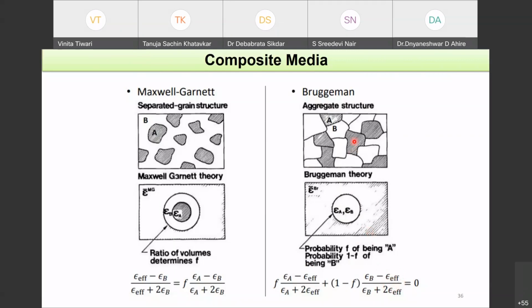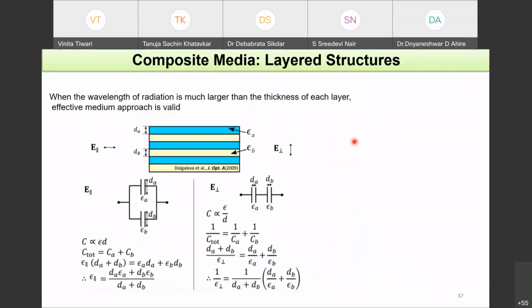When you have a multi-layered structure, which is periodically repeating like high, low, you can have the electric field along the interface or perpendicular to the interface. So you can have two cases where in this case the capacitance is basically proportional to the thickness of the layers, and here it is inversely proportional to the thickness of the layers.